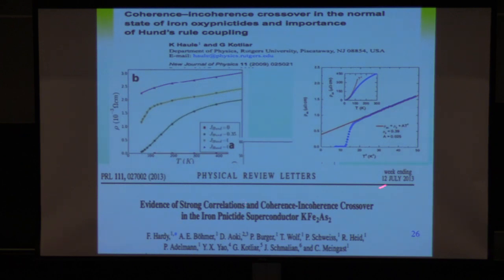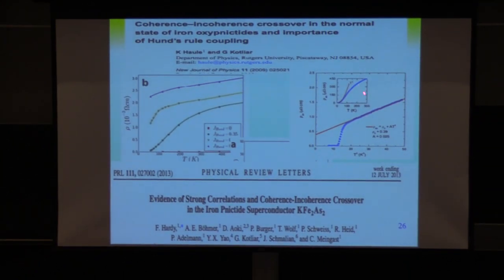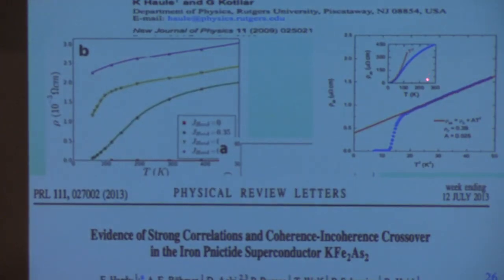And again, a few years later, now people can do good measurements on these iron pnictides and see two things. First, the resistivity at low temperatures is very small. In fact, this resistivity is less than 1 microohm centimeter. It's better than copper. But at high temperatures, it's huge. It's like 400 microohm centimeters. So that's essentially this coherence-incoherence crossover that we had predicted as the materials were discovered. So once again, I think that it allows us to demonstrate that this method now is working really well.